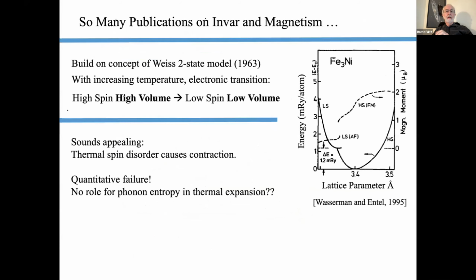So this counteracts somehow a lattice behavior. And this was put together, especially in 1963 by Weiss, who published in the Proceedings of the Royal Society, London, I think, saying that there's a two-state model, high spin, high volume at low temperatures to low spin, low volume at higher temperatures. And this sounds so appealing that it's led to a lot of other computational work. And here's an example of one of the early electronic structure calculations in polarized states. You can see there's a high volume preference for, say, larger spin and lower spin, smaller volume down here, and a couple of minima in the potential surface.